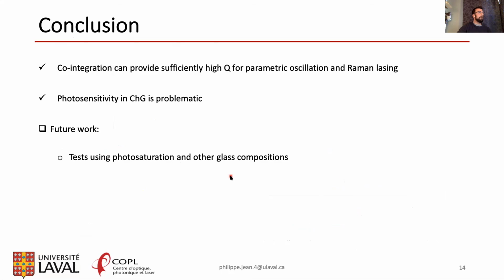Okay, so in conclusion, we demonstrated that co-integration of nonlinear material can achieve sufficiently high quality factor to enable parametric oscillation and Raman lasing. For the specific case of this work where we use chalcogenide, photosensitivity and the overall stability of the glass was a problem for realistic application, let's say. So in our future work, our plan is to test with potentially photosaturation to bring the glass to a photostable state, or to explore other glass compositions that don't have this problem.